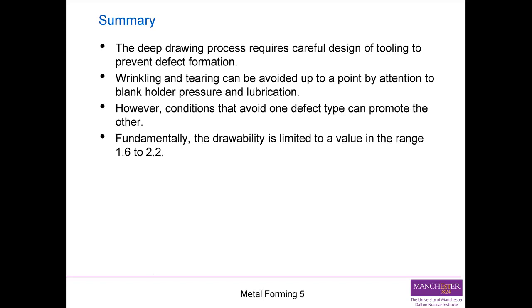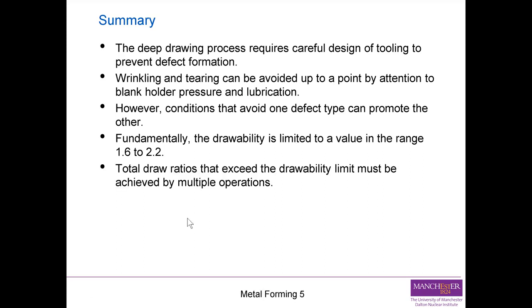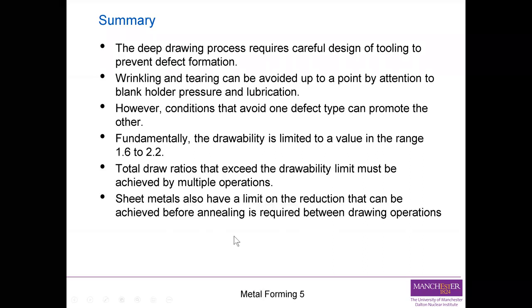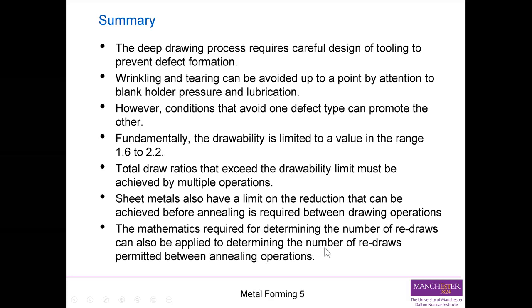Fundamentally, the drawability is limited to a value in the range of 1.6 to 2.2. Total draw ratios that exceed the drawability limit must be achieved by multiple operations. Sheet metals also have a limit on the reduction that can be achieved before annealing is required between drawing operations. And the mathematics required for determining the number of redraws can also be applied to determining the number of redraws permitted between annealing operations. So that's the end of the presentation.